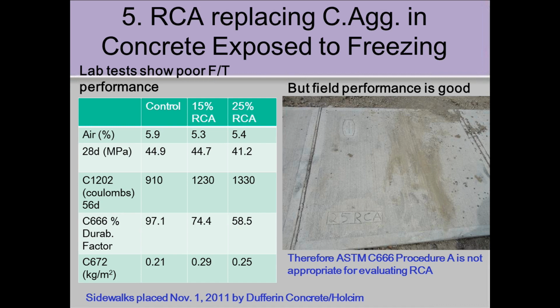That's just dirt sitting on top because I didn't have a broom with me. You should always go prepared to the field. But what you see here is the field. There's absolutely no scaling, there's no pop-outs anywhere on that surface, and you'd expect, if it was going to get exposed to freezing with porous recycled aggregate in there potentially, you could have pop-outs. We didn't see pop-outs after a year.